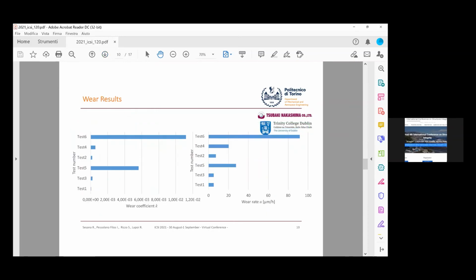For the analysis of the delta volume, the two different volume loss estimations proposed in the two standards gave results with a difference lower than 8%. As reported, this difference does not affect the discussion of results, and both formulations can be applied to compare the wear performance of the investigated coatings. Then, through the values of volume lost by the balls, according to the ASTM G99, the wear coefficient K and the wear rate of the 6 tests were calculated using the Archard equation.